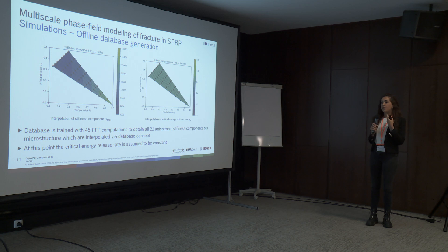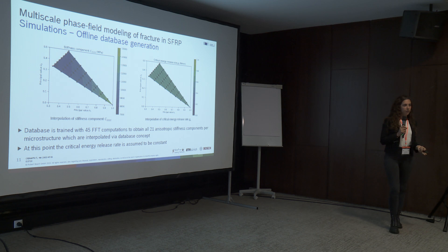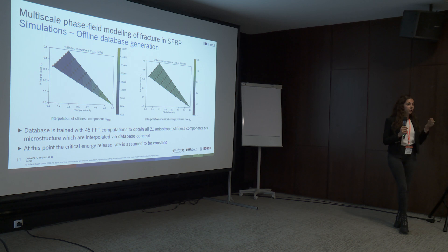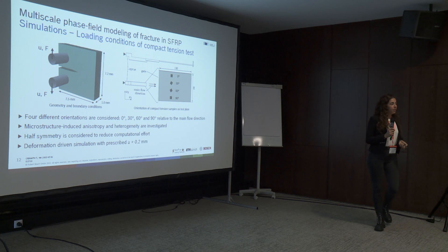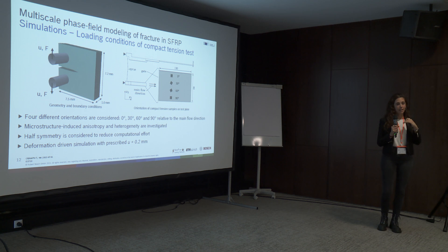This is a visual representation of how the parameters vary within the triangle. We currently use 45 different microstructures, meaning the triangle is discretized into 42 smaller triangles. You can see how the first component of the stiffness matrix C1111 varies with lambda 1 and lambda 2, and the other components vary similarly. Gc shows no variation since it is constant. We then perform some preliminary experiments — pulling a CT sample with two pins, mimicking what will happen in the laboratory.